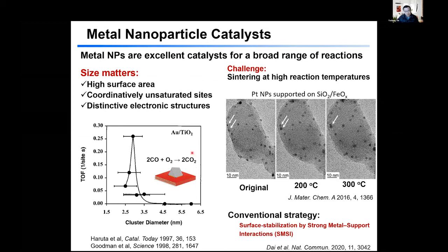The challenge of these metal nanoparticles is that they are usually used not in solution, but on supports. So there's a sintering problem, especially if the reaction runs at high temperature. This is our own example. We put platinum nanoparticles on a silica oxide substrate, and you see these two particles. When we heat up to 200 degrees C, you already see that these two particles get closer, and at 300 degrees C, they merge and become a larger one.